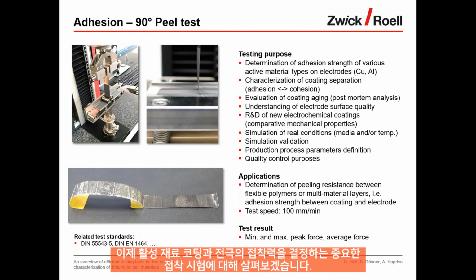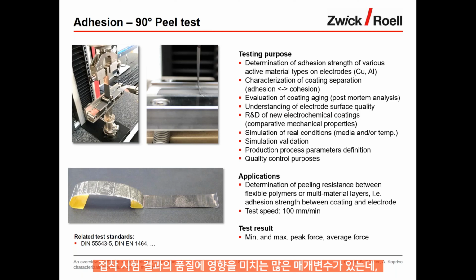Then we're coming to a test which is very important. It's the adhesion strength determination of active material coating on electrodes. There are many parameters that influence the quality of the test results. You need to use an adhesive tape, so the tape quality is important, but also the bonding time and the bonding pressure that you use to ensure the adhesion. So the test is fairly easy to use, good for a quick check, but in the end is not extremely repeatable and difficult to reproduce because there are so many influencing parameters which play a role.